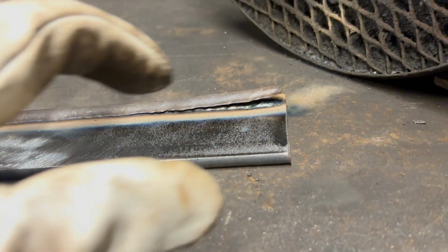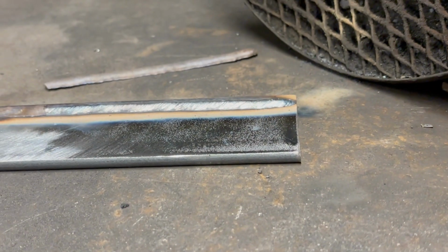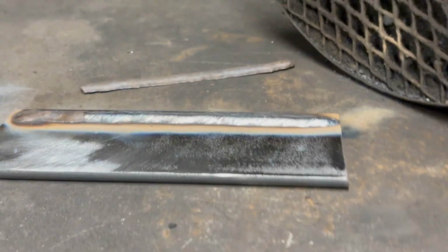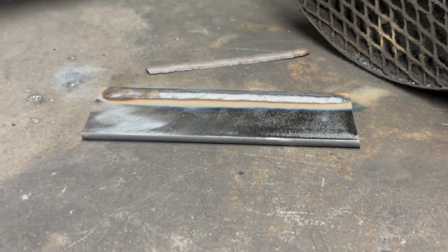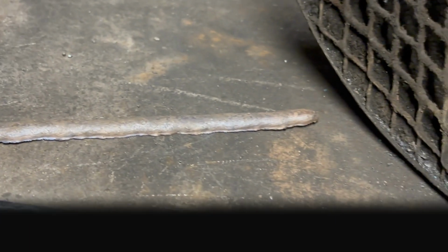So with that run complete, let's take a look at the weld. We've got a nice bit of slag peel going on, which is always great to see as a welder. It's a good sign of a clean, consistent run. The bead looks smooth and even with a good tie-in along both edges, but we can definitely do better than that. The guide range for these rods is 90 to 140 amps, so we're going to max them out at 140 and run another weld using the same technique as before.